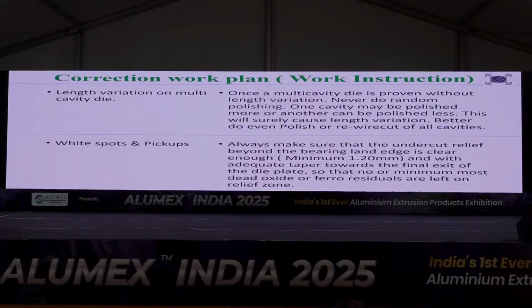Length variation on multi-cavity die, that's a very big problem. Today, it is running with all cavities together in the cooler. Tomorrow, one opening slow, one opening fast. Again, the same problem. With hand polishing in one cavity, if there is more roughness, it will be polished, and the other surfaces will be untouched. There will be no polishing or very soft polishing. It will run fast and slow. So better, if you are planning for a hard polish of a particular cavity, you do wear cut of all cavities equally.